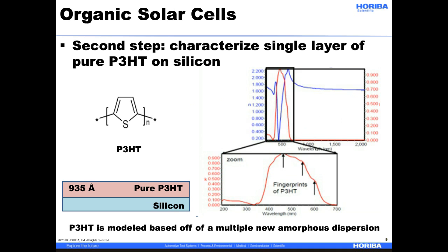The second step here is to characterize a single layer of pure P3HT on silicon. This is 935 angstroms of pure P3HT on silicon, and over here on the right are the optical constants of the P3HT. Just like we did for the PCBM, we look at the fingerprints of the P3HT, the absorption peaks, and what wavelengths they're at. P3HT, just like PCBM, is modeled based off of the multiple new amorphous dispersion function.